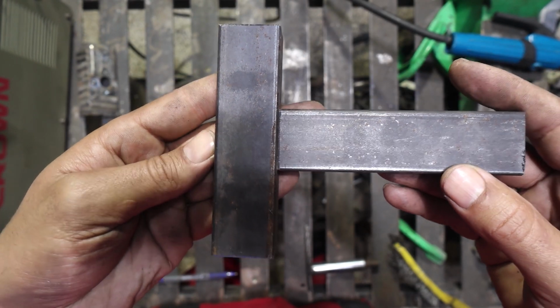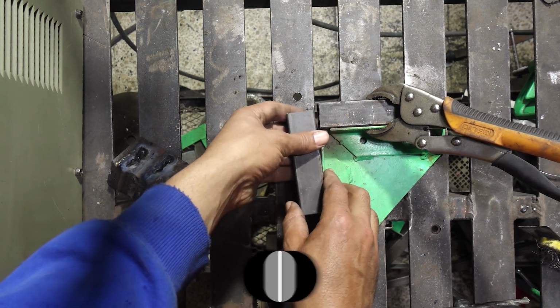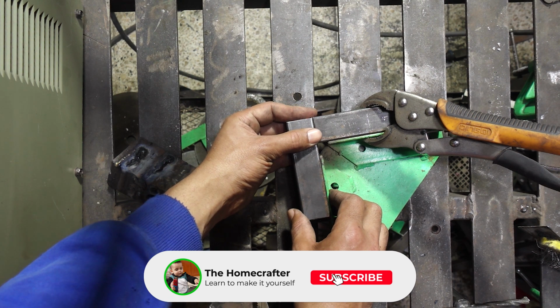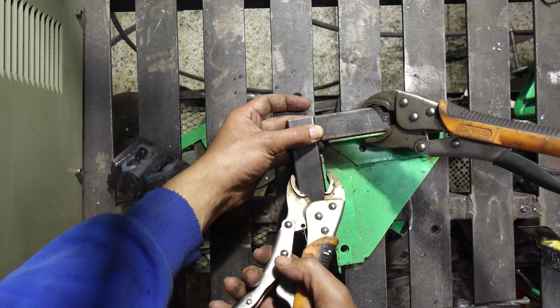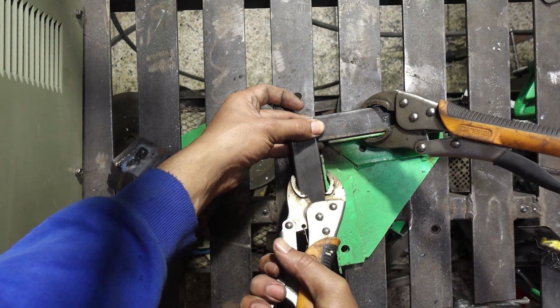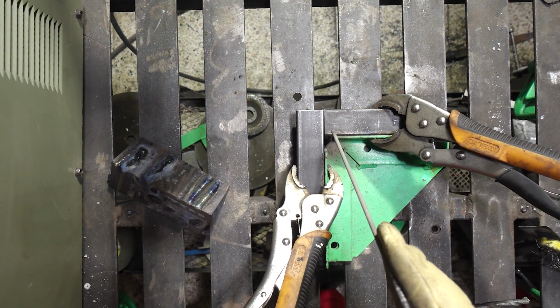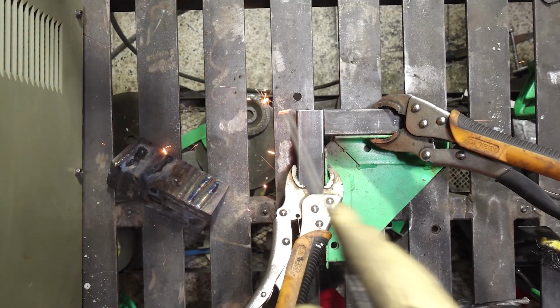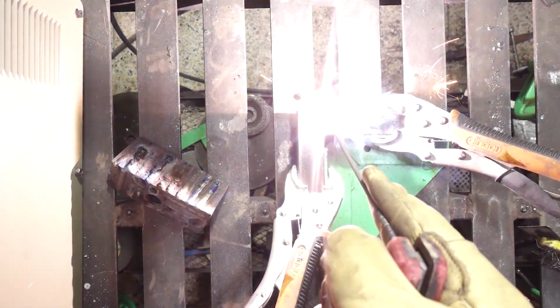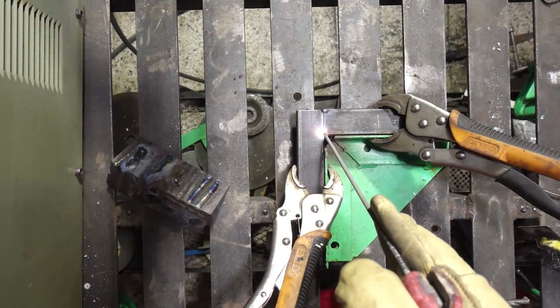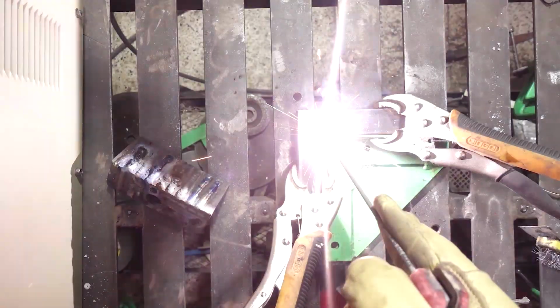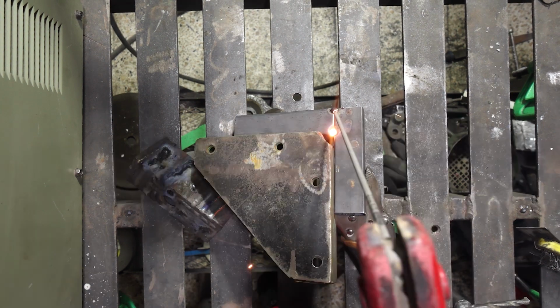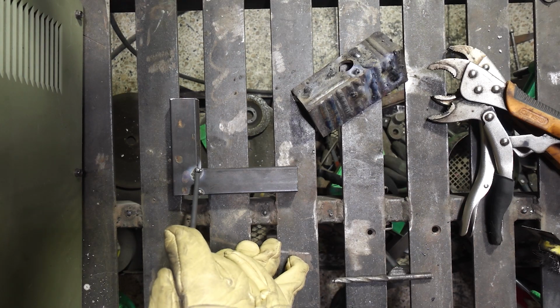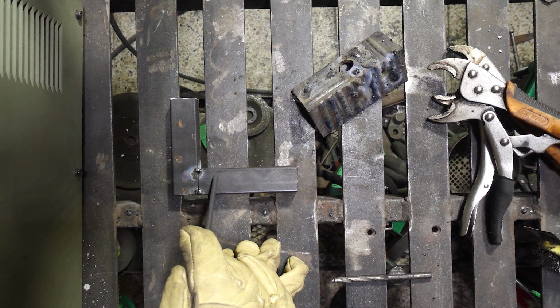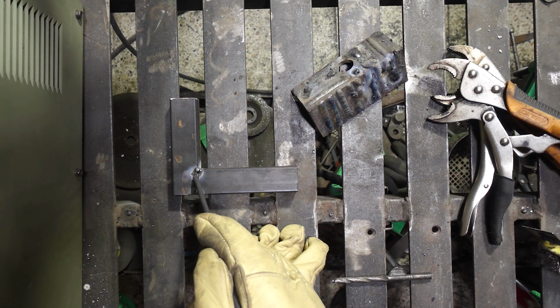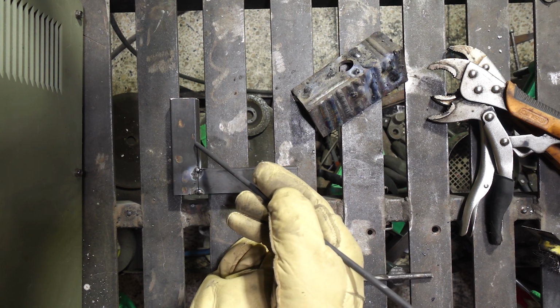Let's weld these two pieces with a continuous weld, but first, let's tack them. To weld like this successfully, we have to concentrate the arc on the thicker edge. While I'm welding, I will lean a bit this way to put more heat on the thicker side.